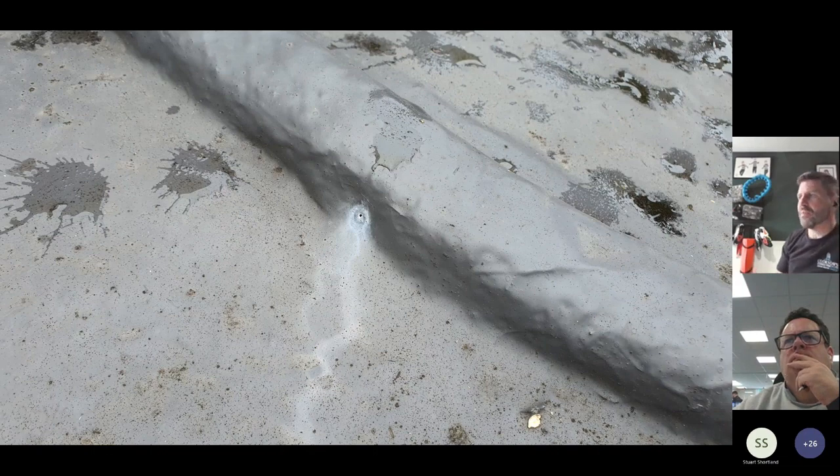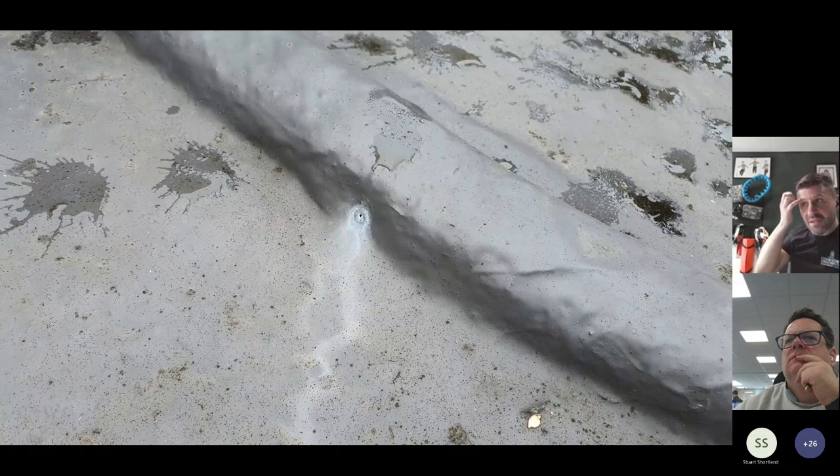In the base coat, pinholes can be remedied. They can be filled with PU sealant or other methods before the top coat is applied. Within the top coat, it's important that we then check the top coat for pinholes, and again, we can fill them with a sealant, or we can put another layer over the top.